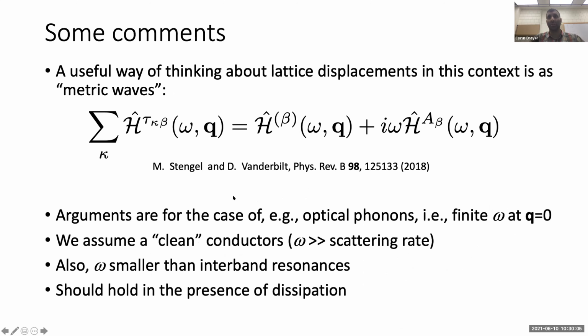So just a few other comments about the results. Our arguments apply to the case of, for example, optical phonons, which have a finite frequency at Q equals zero. The reason being is, you may have noticed, we took the Q goes to zero limit first, and then the omega goes to zero limit, and that ordering was important.